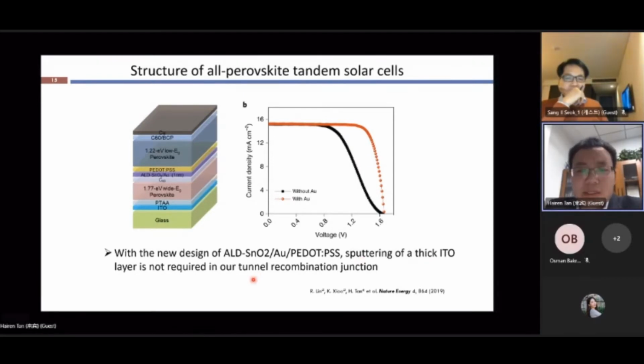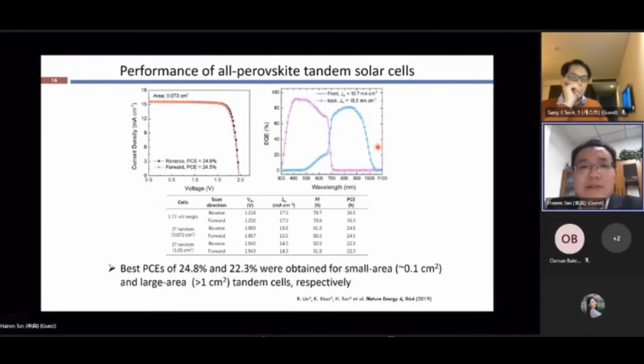So to increase the charge carrier recombination, we deposit another very thin layer of gold by evaporation on top of the tin oxide. This strategy will increase the fill factor of the tandem devices considerably. Then we tune the thickness of the two subcells to get current matched condition, and then we can get a tandem device efficiency close to the record at that time. And we also make even larger area devices by increasing active area up to 1 square centimeter. So we can still get efficiency higher than 22%. And at that time, it's quite promising.